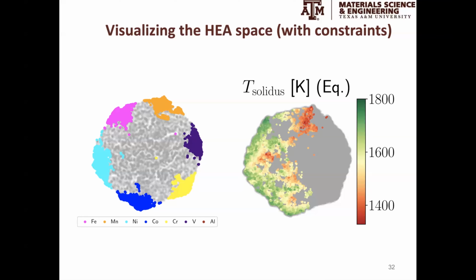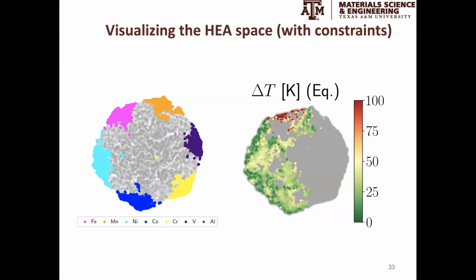If we look at the solidification range, again no surprise: it turns out that less complex alloys have narrower solidification ranges, and the pure corners have probably the narrowest solidification range, as it should be. The more complex alloys tend to have slightly larger solidification ranges.